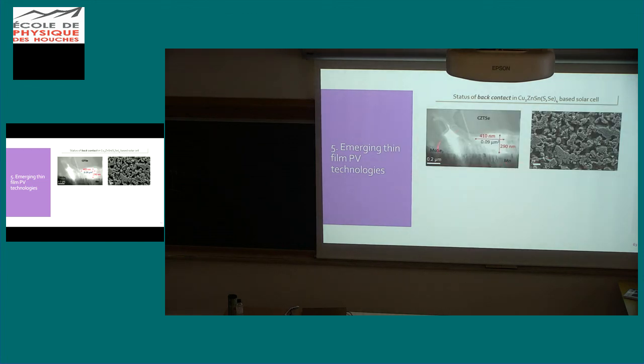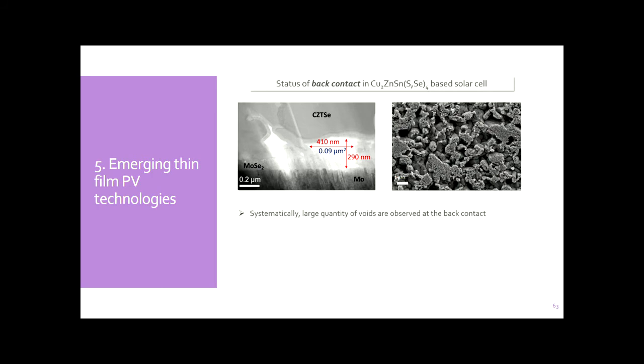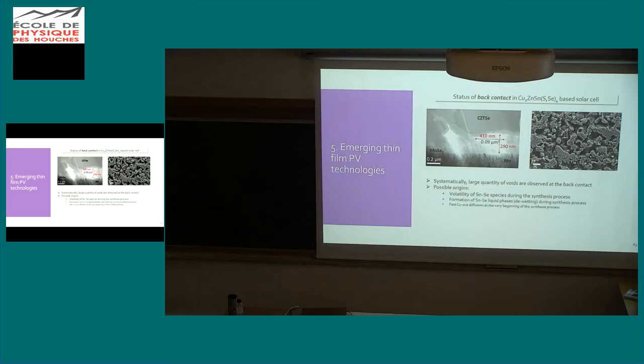But even if we take a look at our back contact, we observe a lot of voids. The reasons are mainly these three, in order of magnitude. The volatility of tin selenide species is the main problem. Then the formation of some tin selenide liquid phase that cannot wet the substrate very well, and a fast copper out-diffusion during the synthesis. But the main one is the tin selenide or tin sulfide volatility.